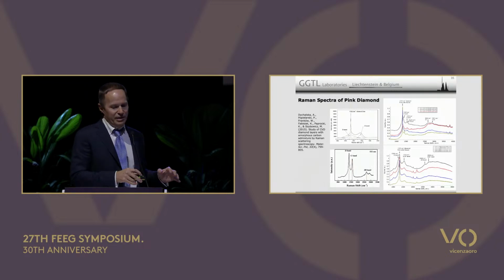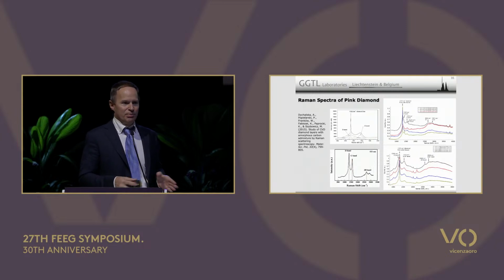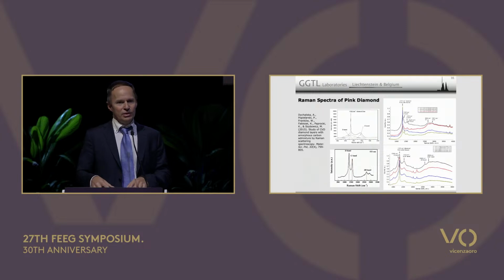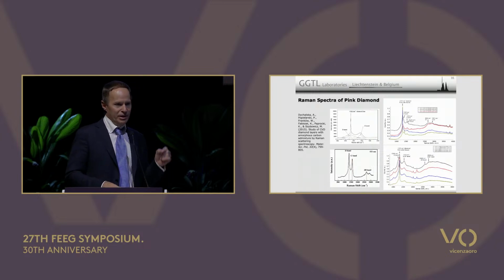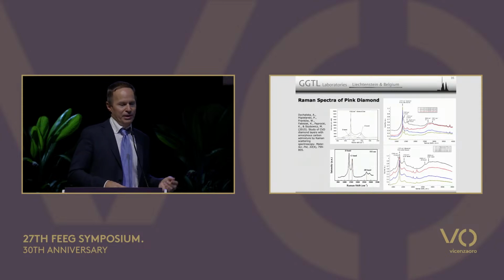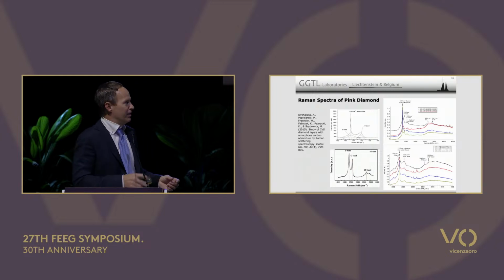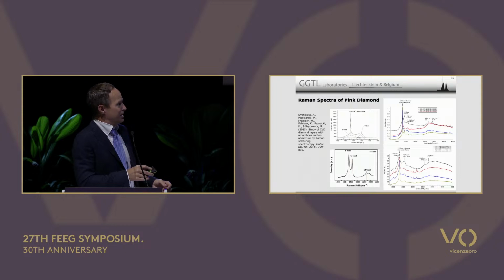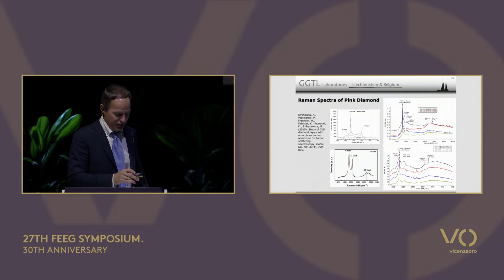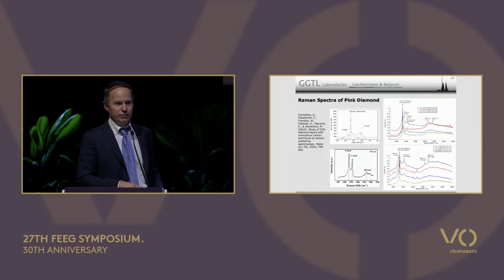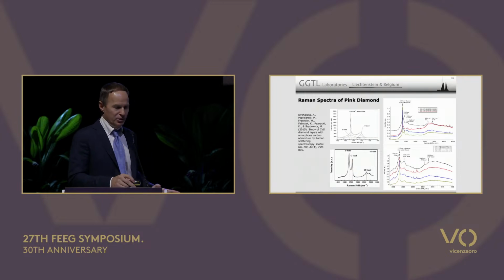Now we still have to go on to understand it further. Here we use the 635 nanometer laser, and that laser has a pretty poor quality. The Raman quality of a spectrum correlates directly to the laser quality. If you have a good laser with a narrow laser line, the Raman bands will be narrow. If your laser is terrible, so it has a large band, your Raman bands will be wider. So between 532 and 635, the bands all got much broader, which is proof that this is Raman signal and not photoluminescence signal, because photoluminescence is independent of the laser quality. It doesn't matter if your laser is good or not, your stone will fluoresce.